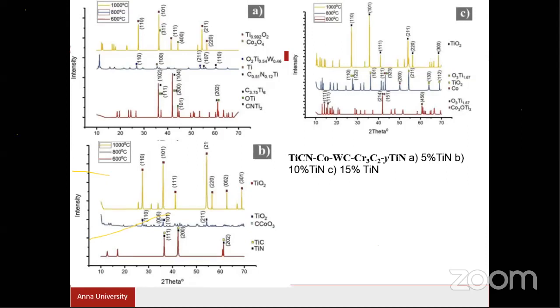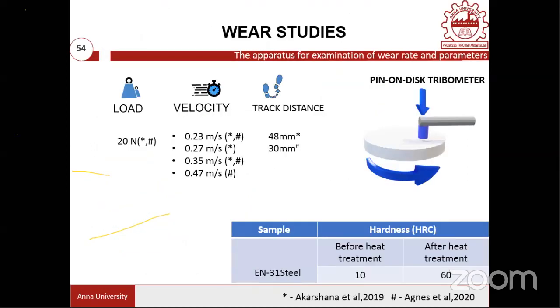So this shows that the tool that we have proposed is stable up to 800 degrees centigrade. Probably if I conduct another experiment at 900 degrees centigrade, I can give you a very close value of thermal stability, but we have not conducted this 900 degrees centigrade experiment. It's in process. Because it's a lot of trials that we have to do, we have limited the number of experiments. Now, another experiment is the wear studies.